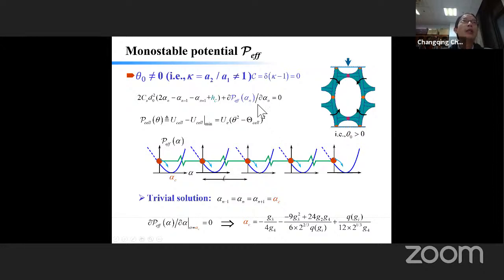Usually we cannot get the analytical solution for this equation, but we can consider a trivial solution. Basically, we assume all rotations of the unit cell are equal. So basically, we have alpha 1 equals alpha 2 equals alpha n, equal to a constant. Then we substitute this solution into this equation. We come out with alpha c. So basically, that means all unit cells deform by the same amount of rotation, which is given here. G2, G3, and G4 are all already determined parameters.